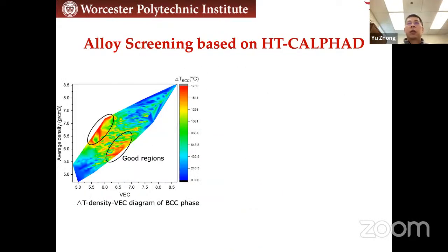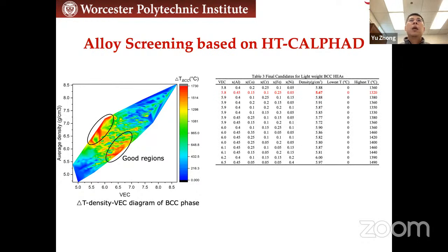With those several thousands of compositions, we can do the screening based on our criteria. For example, the color bar here shows the stability range for BCC, the temperature range. The red one means it has a very wide range where BCC is stable, and the y-axis is density, right? Based on this, we can get what I call a refractory alloy, also with a very low density. When I say refractory, it means its melting temperature is very high. These are the compositions we have screened out, and especially there is a red one.